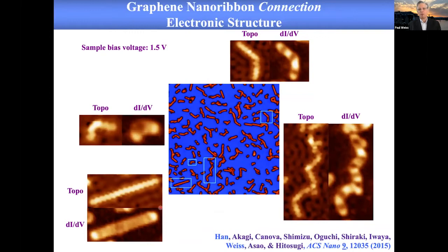So in the straight graphene nanoribbon, for instance, we can show the continuity of the molecular orbital. And I'll point out that we can measure the phase of the molecular orbitals as well. And it's a much longer story, but those of you who know me know that I have PTSD about phase. And so I insist that we always measure the phase in these contacts. So for instance, this U-shaped nanoribbon looks in topographic measurements with the STM as if it's good. But when we look at the phase, we see there's a node at the contact. And so that is not what we want for a contact for these systems. And you know, all these stripes are indicative of nodes. And that tells me that that isn't what we wanted.